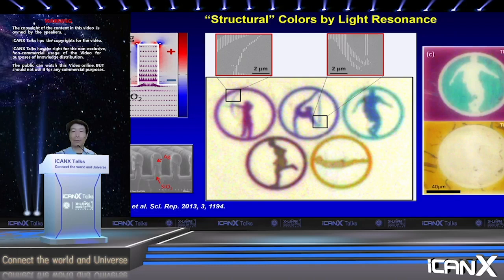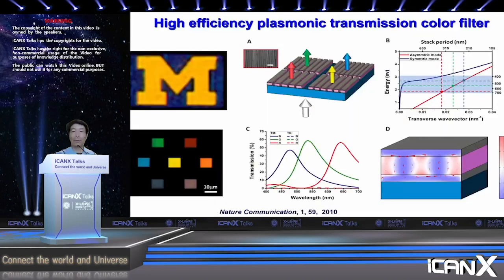Now, this is a reflection type. And the earlier work that we did is actually a transmission type, shown in this slide. So in the middle, that's the structure. It's very simple again. It takes two metal layers sandwiching a dielectric layer. Now, if you don't do anything, it's simply a mirror. In this case, I think we used aluminum. So it's actually reflecting very well.